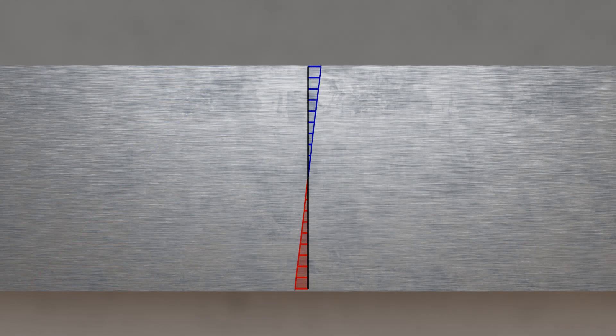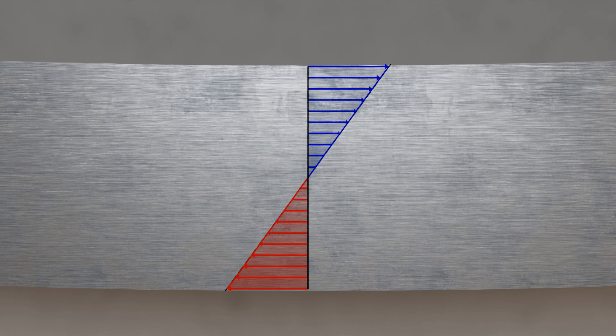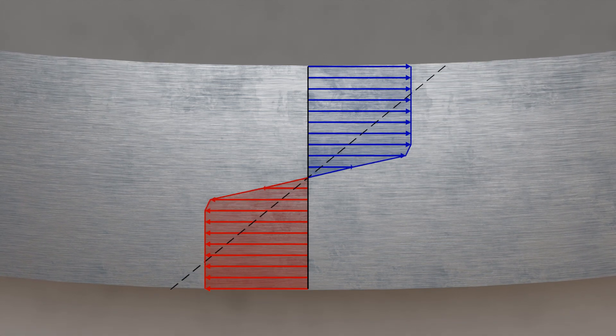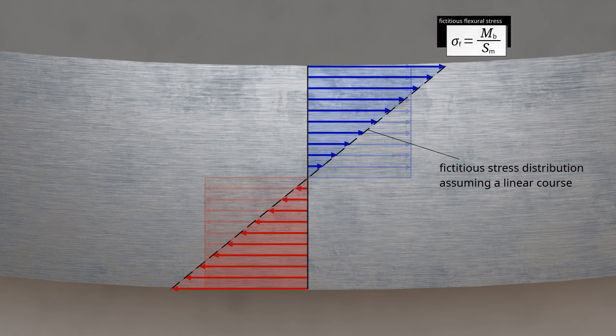As already explained, the stress distribution in the cross-section of a specimen subjected to elastic bending has a linear course, provided that Hooke's law applies. However, this changes when the flexural yield point is exceeded. For materials without strain hardening effects, the stress in the outer areas does not increase further when the yield point is exceeded. If the bending moment is increased further, the areas further inside are also stressed only to a maximum of the flexural yield point. The fictitious stress distribution, which generates the same bending moment as the actual distribution assuming a linear course, is shown as a dashed line. If the formula for flexural stress were used at this point, the result refers to this linear distribution — the calculated flexural stress is therefore only a fictitious bending stress and does not correspond to the real stress.